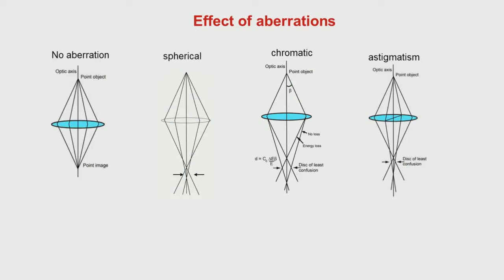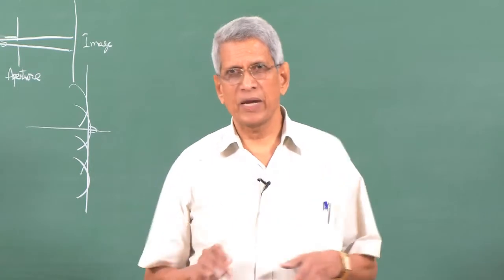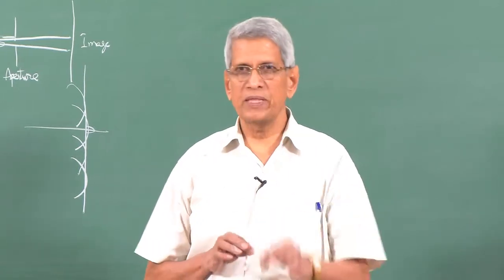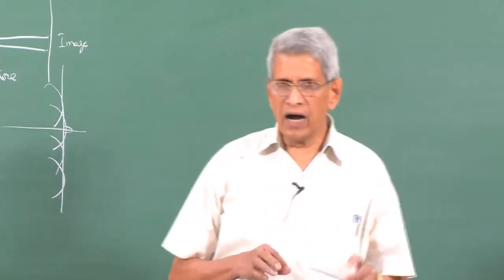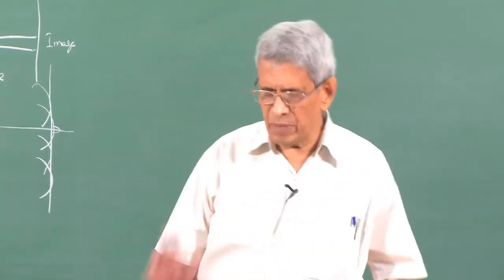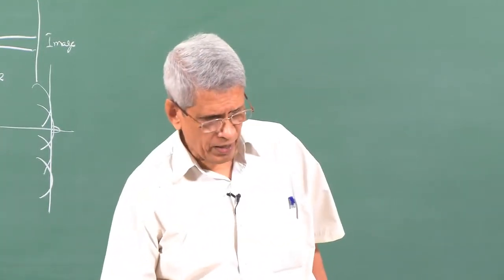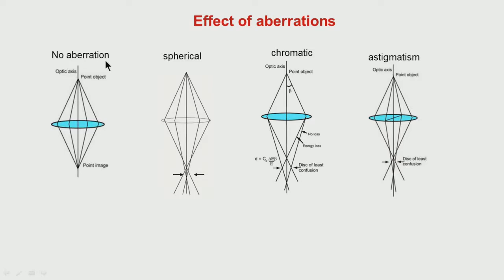Now, no lens is perfect. All lenses have some aberrations associated with them. What will be the effect of that aberration on the image it creates? For a point object, for an ideal lens, a point image should be formed. That doesn't occur, and the Rayleigh criterion tells what that value should be, and that turns out to be this, 0.61 lambda by beta. This is the first criterion.